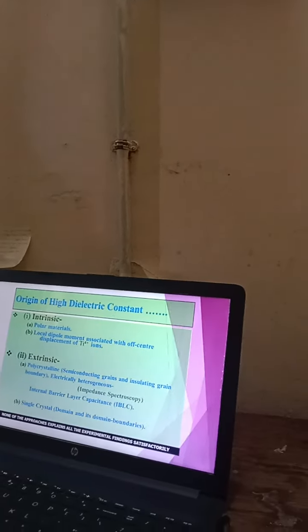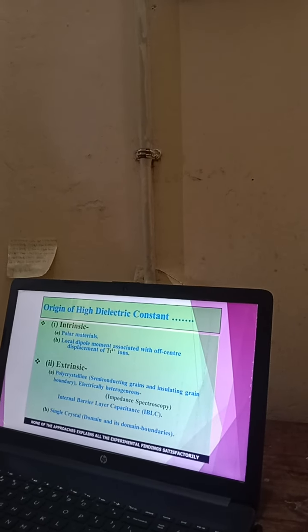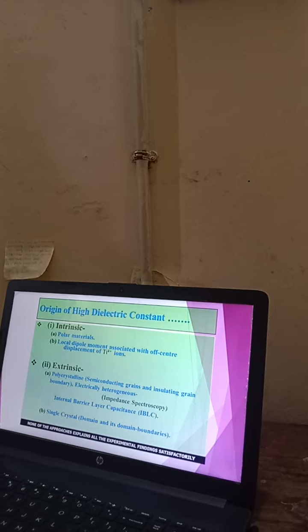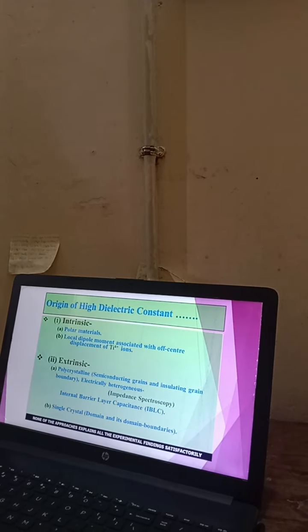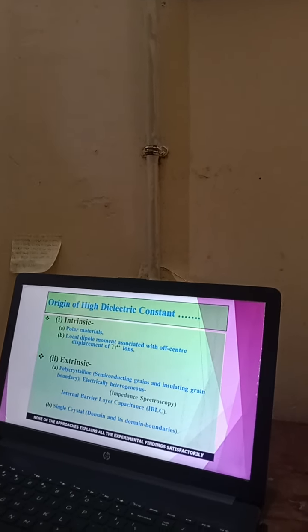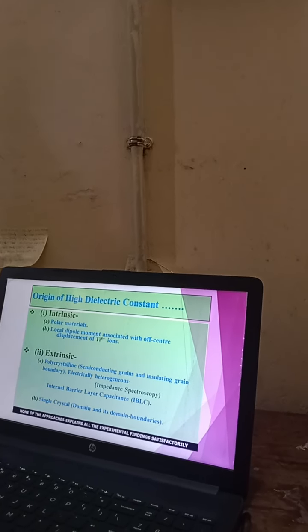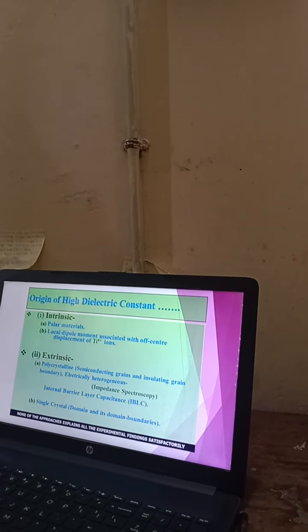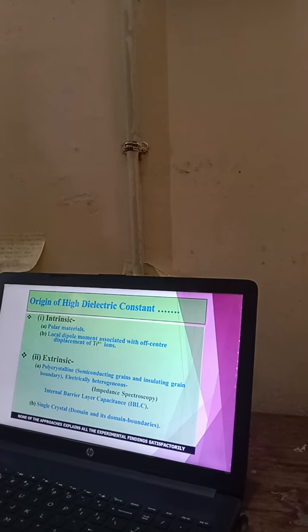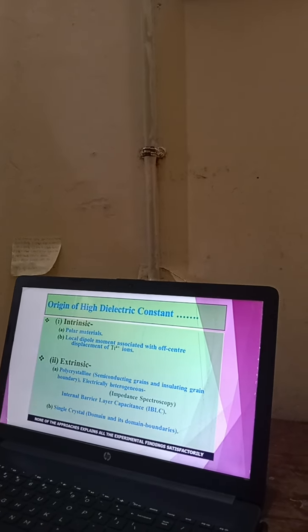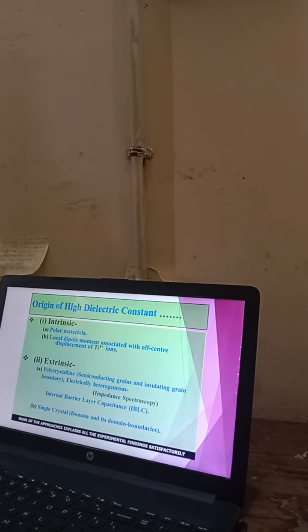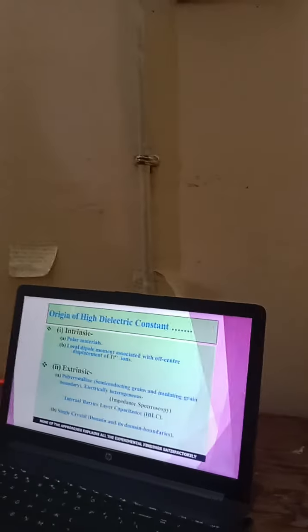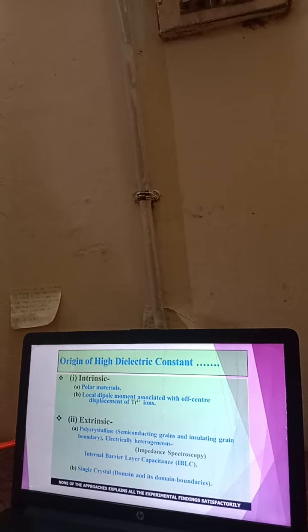So this slide represents the theory that explains the origin of the high dielectric constant. There are two theories. First is intrinsic, second is extrinsic. The intrinsic can be divided into two parts: the material should be polar, and the local dipole moment associated with off-center displacement of the titanium 4 plus ion.